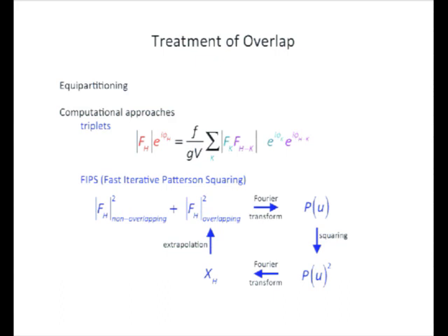And these, of course, correspond to our starting point, our amplitudes. Those which are not overlapping, you don't do anything about them. But you take the coefficients that were here to repartition the overlapping reflections. It turns out that the direction of the change is correct, but not strong enough, so there's also an extrapolation step involved. If you have enough non-overlapping reflections, you can do something about your overlapping reflections, and you go around and around until the statistics here approximate the statistics of your non-overlapping reflections.